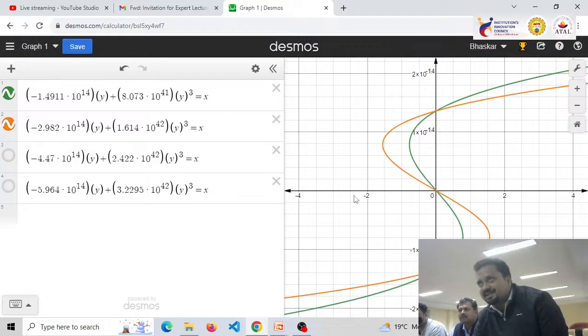Now here also you can see in this range, if you see the gradient or slope of this characteristic, it's negative. So it means I'm increasing the voltage. The value for this curve is TFE equals 16 nanometers. So the previous one, the blue one, was for 30 nanometer. This is for 16 nanometer ferroelectric thickness. Okay. So now you can see the slope or gradient of this particular line is negative in this particular region.